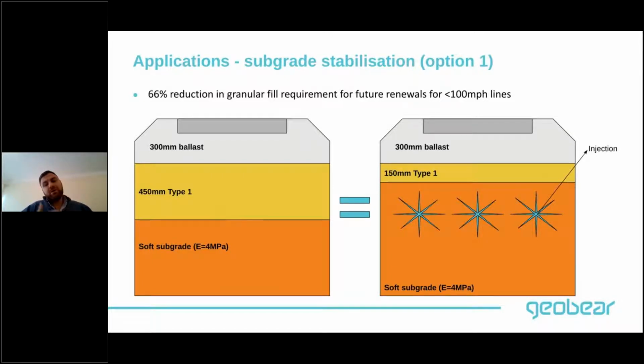However, if you decide to use geopolymers just before the renewal, for example, you can inject the geopolymers in this sort of manner with a certain quantity, and you can reduce the thickness of the type 1 requirement from 450mm to 150mm. So therefore, you have saved on the excavation. You don't have to do deep excavation, and as a result, you're going to save on logistics, spoil removal, and all that. And also consequently your carbon footprint, because you're not going to require the same amount of possession, and logistics. So that's one way of using it.